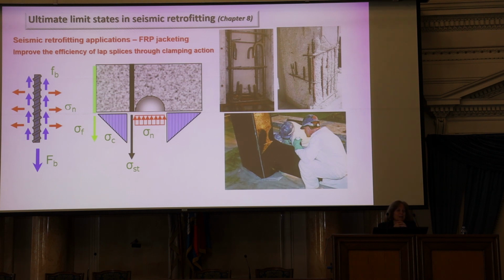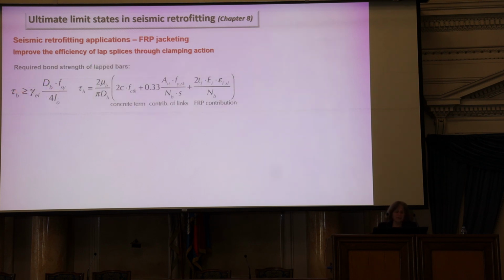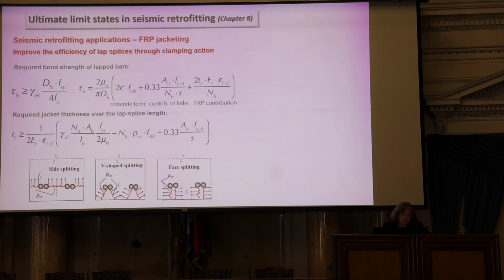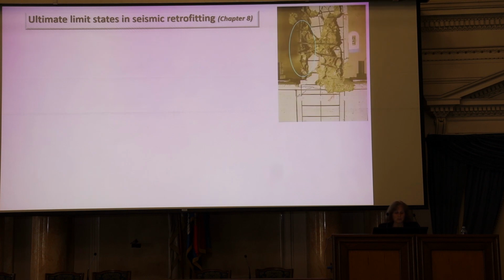And by engaging the transverse jacket, this returns back to the bar through a confining pressure. And so there is a very simple frictional mechanism that enables the clamping action. And so you can actually determine how much bond strength you need in order to develop your reinforcement. And as you will see, the last term in this expression tells you what the jacket component is. Therefore, if you know the strength that you need, you can figure out how much jacketing you need to add.